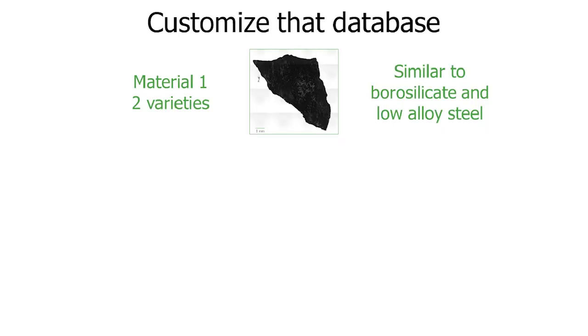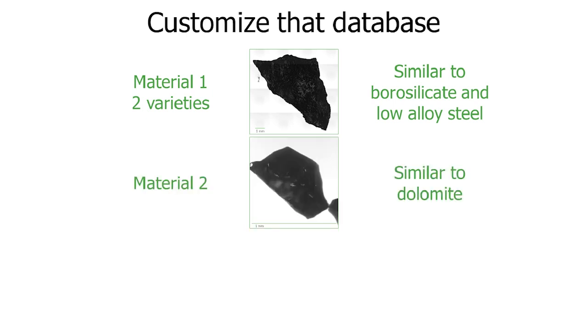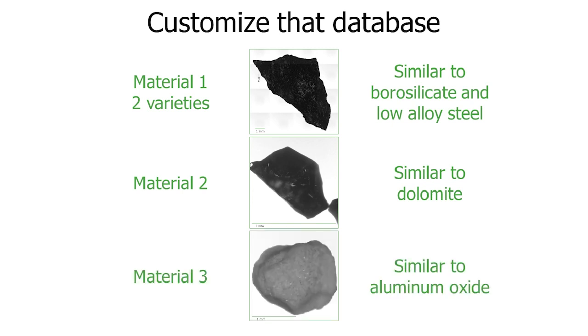The first raw material actually ended up having two varieties. The outer layer of this was similar to borosilicate, while the inner layer was similar to low alloy steel. And both of these varieties were added to the custom database as materials 1A and 1B. Material 2 was similar to dolomite, while material 3 was similar to aluminum oxide. All of the raw materials were added to a custom database, and the 3 structural debris samples were then compared against that database for a specific breakdown of how much each material is present in the structural debris sample.